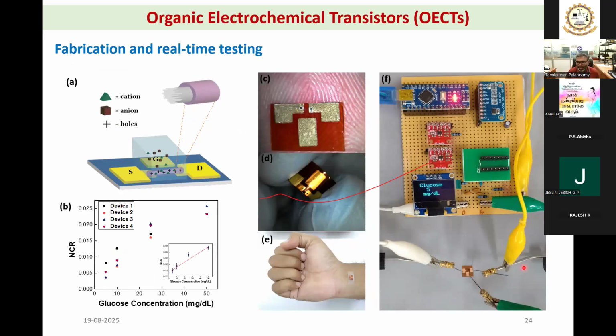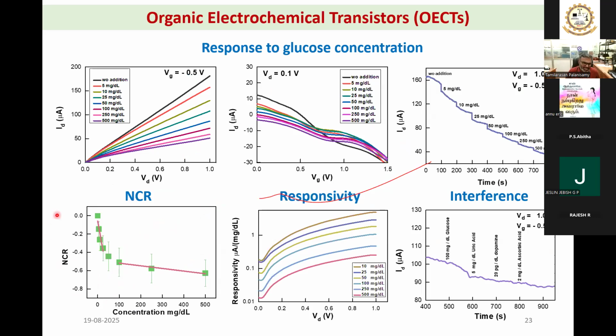which is very easy to handle with normal electronics. So we made our electronics as well as our algorithm, and we got this response. You can see here, when the glucose concentration increases, the response increases, the net current response increases. From this NCR curve, what I wanted to highlight here is the response, the change in response when you change the concentration is very steep at lower concentration. And it is still changing, but the slope is less here. The slope is very high here.